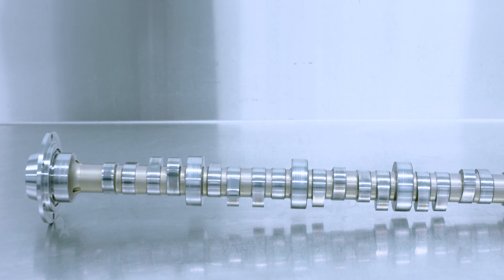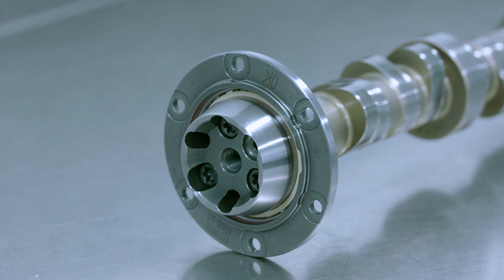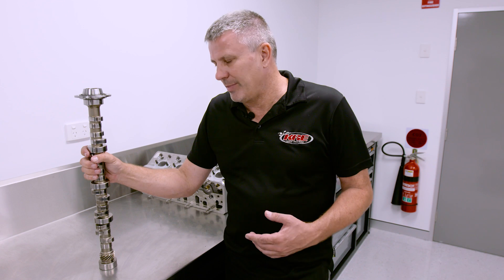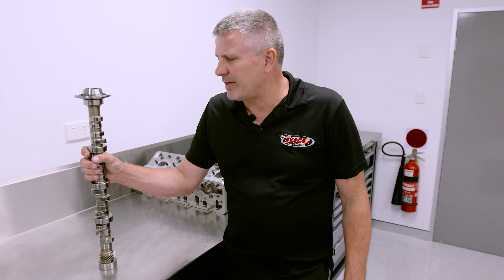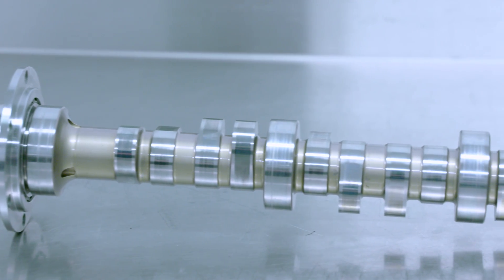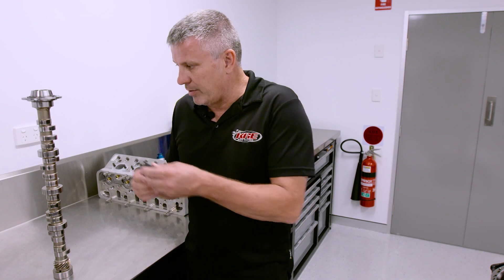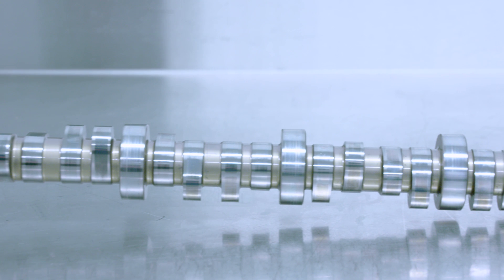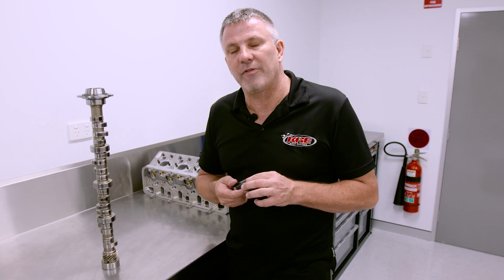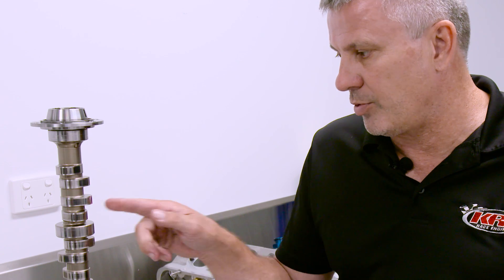The camshafts we use in the supercar engine are a control camshaft from CompCams in the US, made to a spec for supercars — everyone buys off the same supplier. These run a zero thrust hub on the front, so we have no endplay. In the old days when we had freedom for camshafts, we made 15 to 20 more horsepower, but we broke some stuff. Supercars put this rule on, I think it was six or seven years ago, and it's been good — we sort of gained that power back in other areas. With the camshafts, we found they're quite susceptible to oil. You can see the lines in them. What we found with some oils is the lifter will break down, the needle rollers will start to wear, and then obviously the lifter will skid on the camshaft and fry the camshaft. We normally get anywhere from 15 to 25,000 kilometres out of a camshaft. If the lifter has an issue, we could tear a lobe off in 5,000 kilometres. So the oil is quite important in how it looks after the coating and the needles to make sure we don't wear the camshaft out.